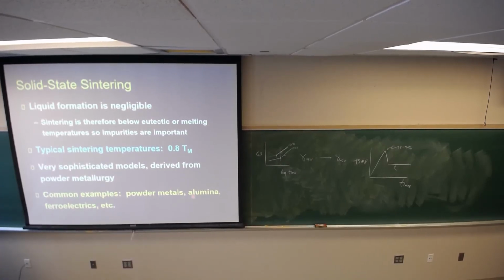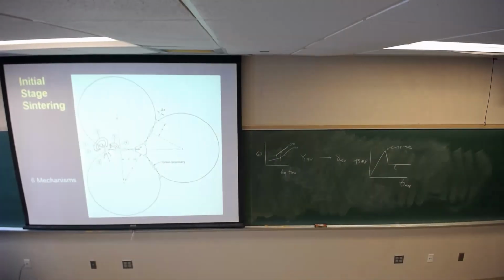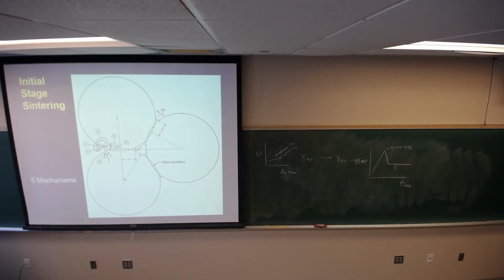Ferroelectrics, things like lead zirconium titanates and what have you, are also argued to sinter by solid state mechanisms. We don't think that's true. Ashby developed this really elegant model. Perfect spheres, of course. There are 6 different mechanisms. Only the mechanisms that contribute to the 2 centers of these particles moving closer together contribute to densification. Everything else is contributing to neck formation.